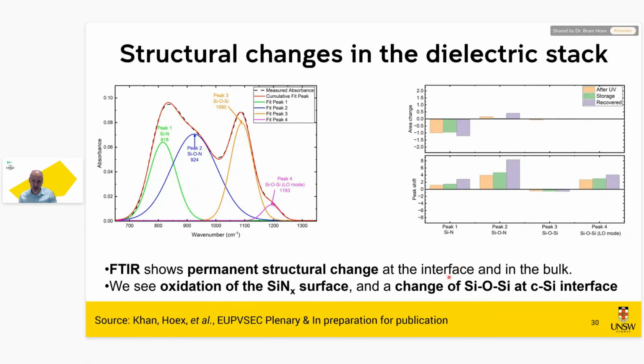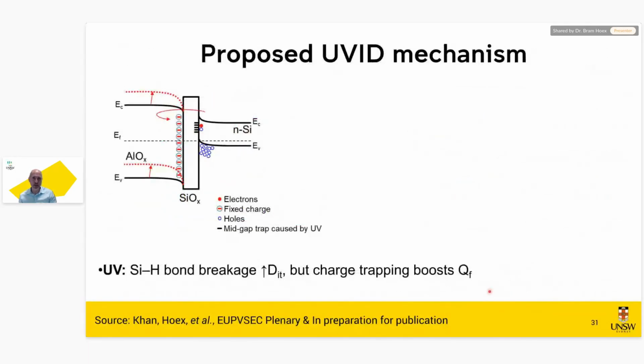What we see in addition is that even though our temperatures are very modest, this peak 4 increases in intensity. So we see changes at the crystalline silicon interface. We see the silicon oxide, like the thermal oxide reported by the Fraunhofer group. We see that UVID, like the various treatments that we do for dark annealing, for example, improves this interface and just makes it better for subsequent exposures. So if we come to our proposed UVID mechanism, it's actually quite simple.